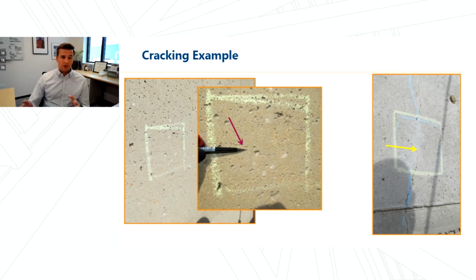So these are cracks on the same structure. I actually took both of these photos from a swing stage drop on the same concrete structure. On the left-hand side, we have this horizontally oriented crack. On the right-hand side, this vertically oriented crack. They're pretty narrow, but if we had very sophisticated visual survey tools, we might capture these with a high-resolution drone, for example. But what do these cracks mean? What do they mean to us as condition assessment evaluators?